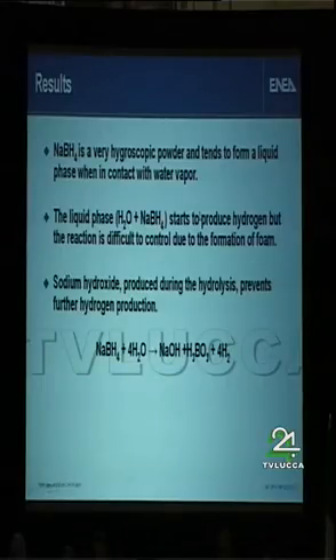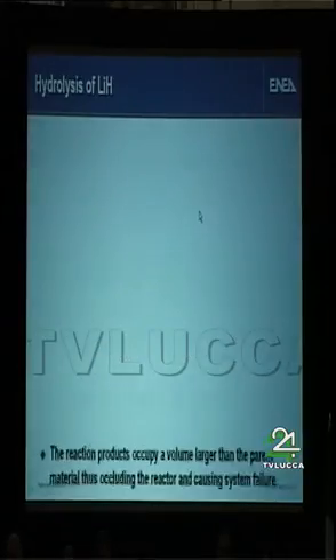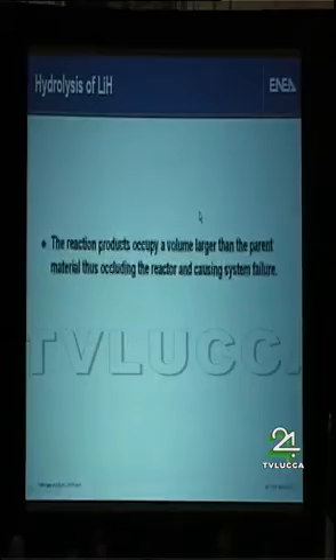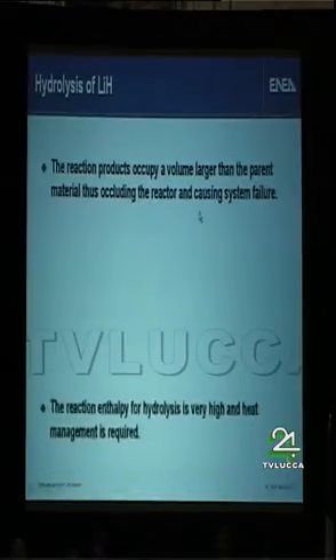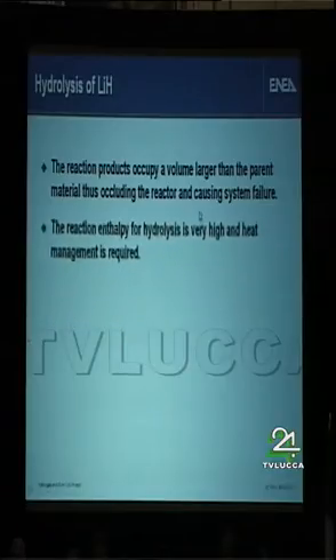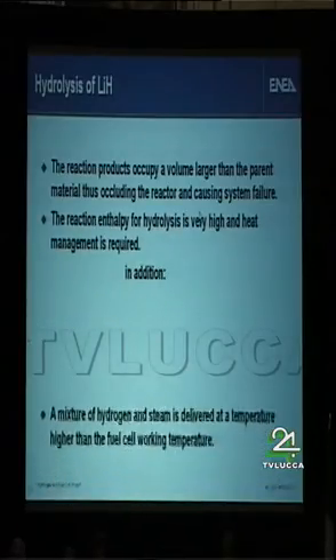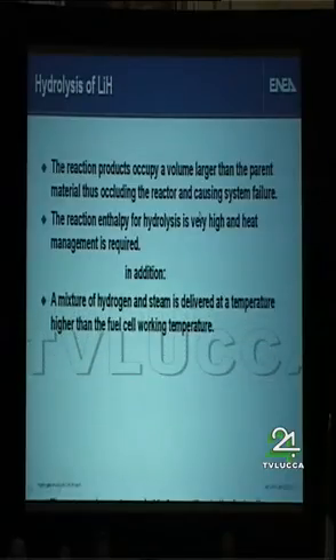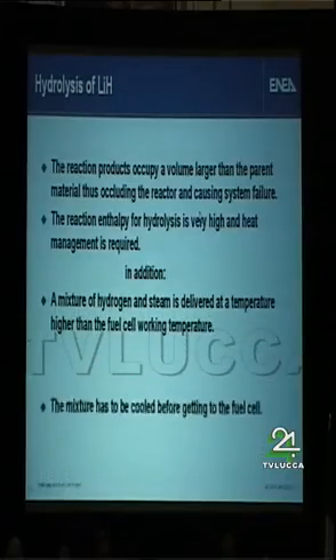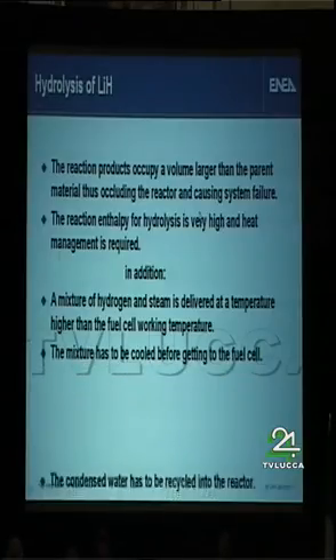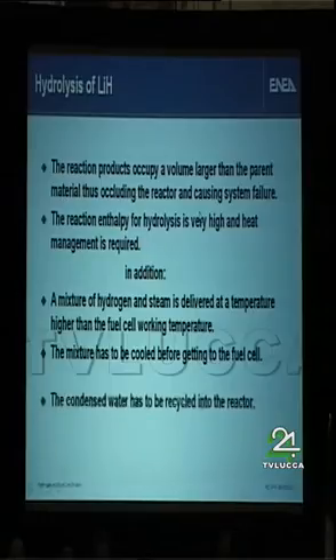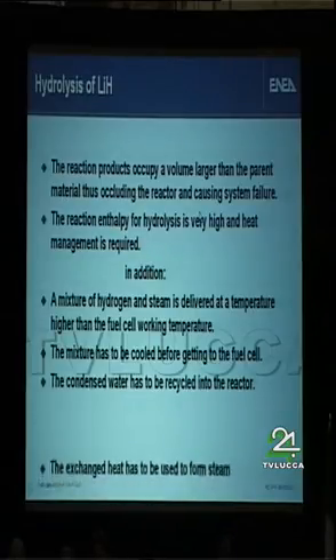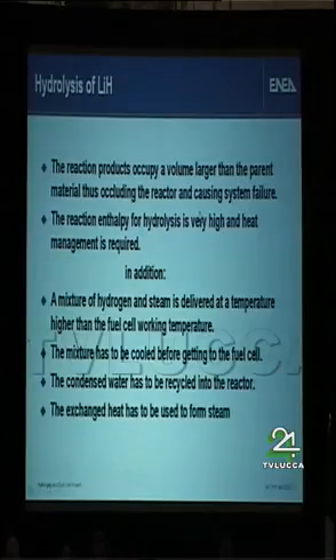Also, the sodium hydroxide that is produced during the reaction stops the reaction itself, and so we encountered a lot of problems. In the case of lithium hydride, the problem that we had is that the volume of the reaction products is larger than the volume of the parent lithium hydride. So in some cases there is a reactor occlusion, and the reaction enthalpy is very high, so we need to refrigerate the reactor. Other technological problems have to be solved.